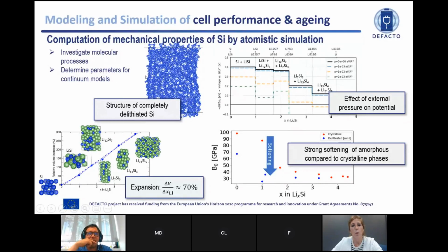So first, we start by running a simulation at the atomistic level, and we come out with some values of the expansion, for instance, at the atomistic scale with the lithiation state. Also, we have applied certain pressure and seen how the external pressure influences the potential, but not the volume. And then we have also analyzed the difference between crystalline silicon and amorphous silicon, because the bulk moduli are completely different from one to the other.